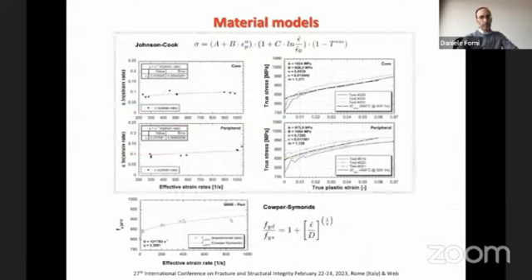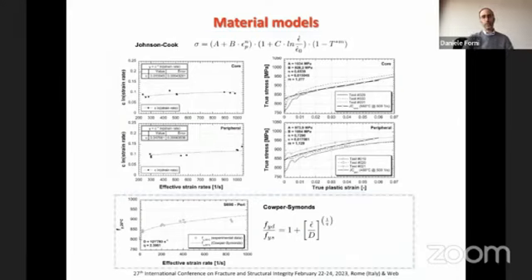So something about the other two models: the Johnson-Cook model, by means of the 5 constitutive parameters, is able to predict the true stress versus true strain in a wide range of strain rate and temperature. As you can see on the right plots, this model is able to fit the experimental data very well. On the other hand, with the simpler Cowper-Symonds constitutive model, it is possible, by calibrating only 2 parameters, to predict the yield tensile strength at increasing strain rate, but in its original formulation only at room temperature.